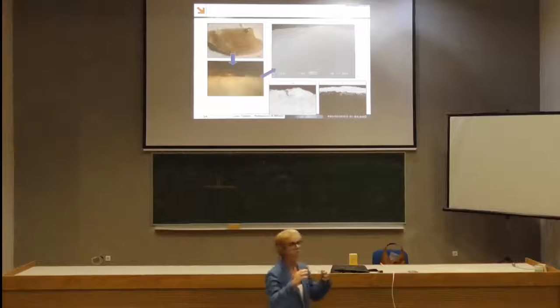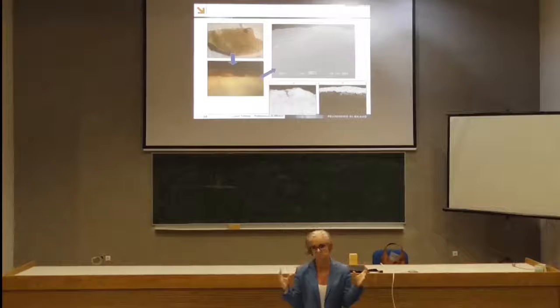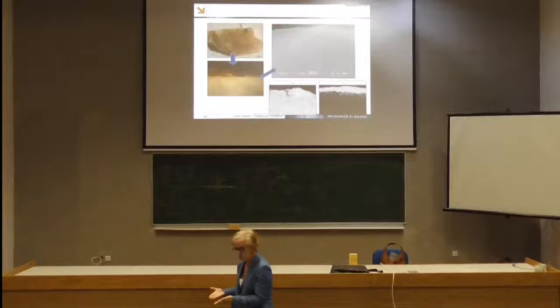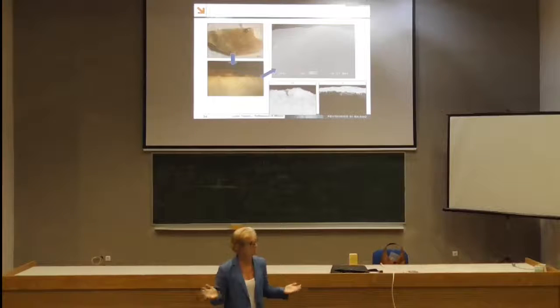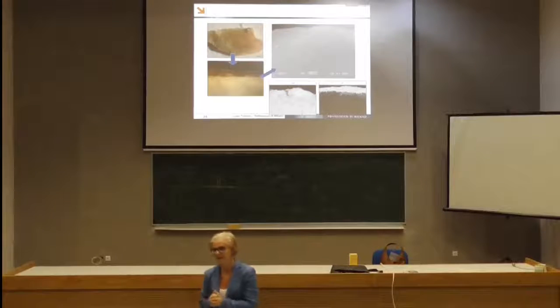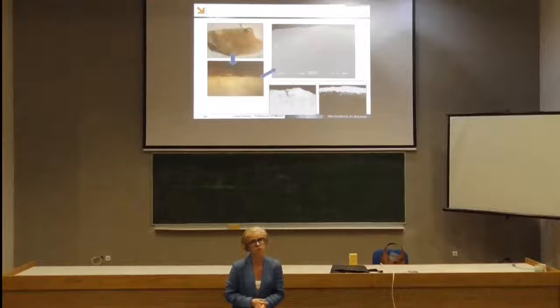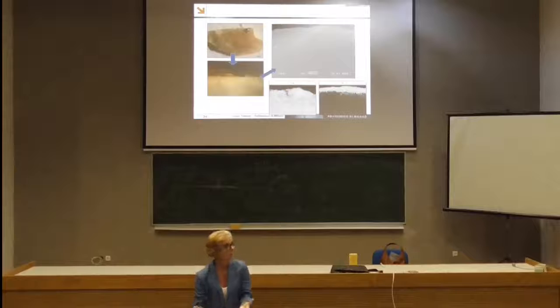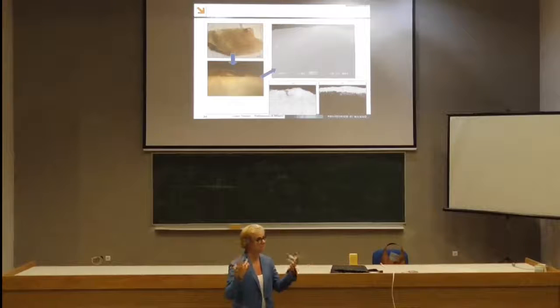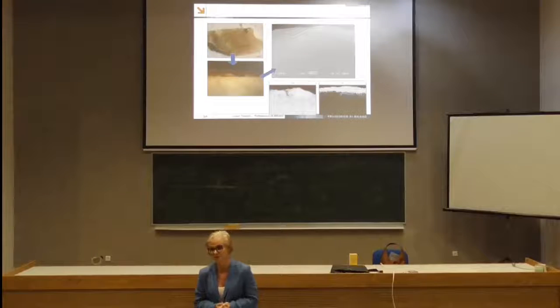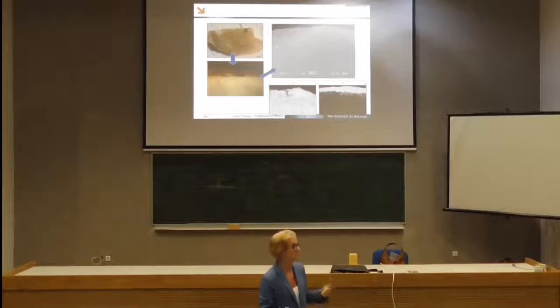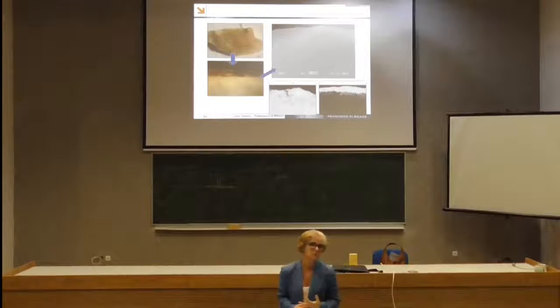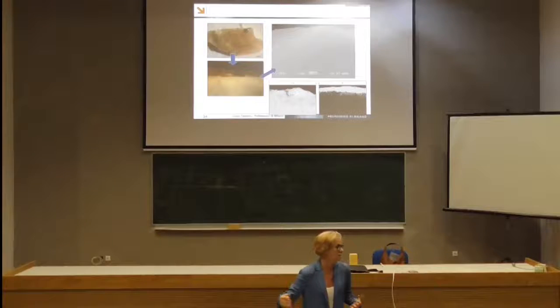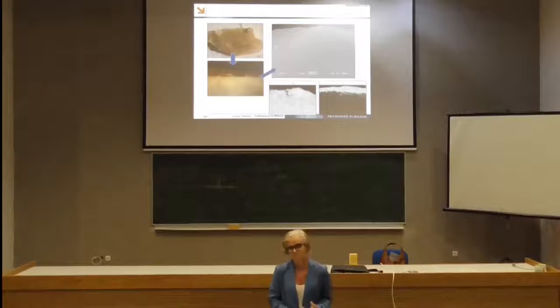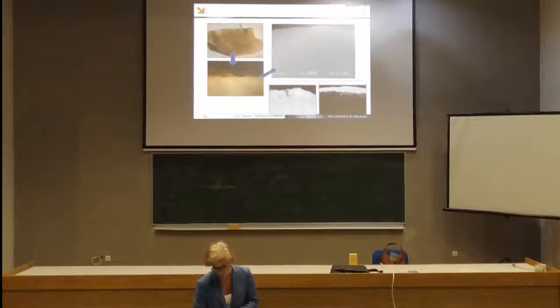There were salts, mostly gypsum, on the marble surface, and they treated everything: marble, gypsum, and all the deterioration material that there was on the surface. So in a certain sense, we had preserved the deterioration materials. We had preserved everything with this acrylic varnishing, and I know that this is not the only case, but it was occurring very often in that period.